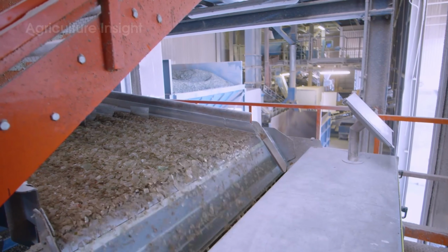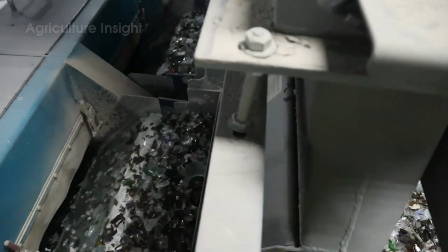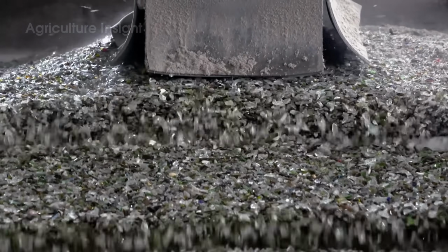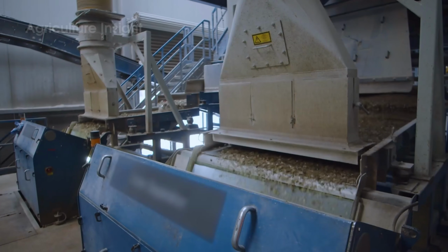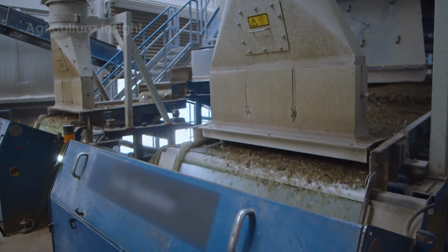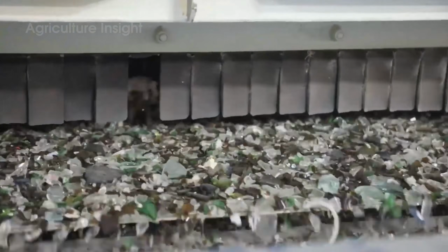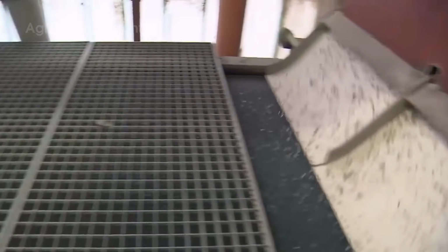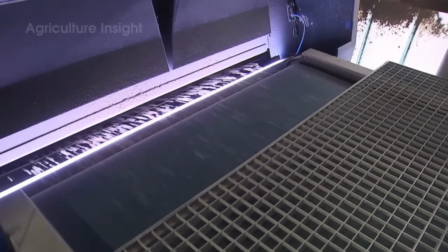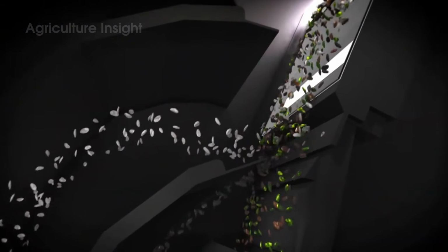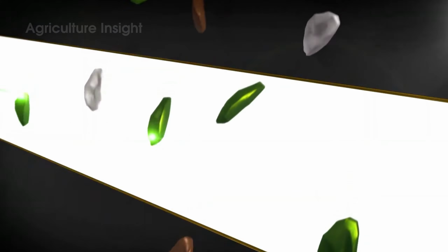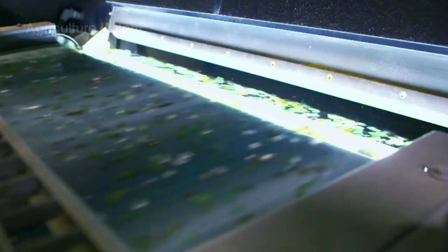The final, and also the most sophisticated stage in the cleaning process, is optical sorting. At this point, glass fragments are spread thin and allowed to fall like a waterfall in front of a system of high-power laser sensors. In a split second, these sensors scan each fragment to accurately analyze its color and material composition. As soon as a differently colored piece of glass is detected, or more dangerously, a stray piece of ceramic, the system immediately activates compressed air nozzles. These air jets fire with millimeter-level precision, blowing the contaminants out of the main stream in just milliseconds. Absolute precision at this stage is vital, because even a tiny amount of color deviation or ceramic contamination can completely ruin the transparency and quality of the entire batch.